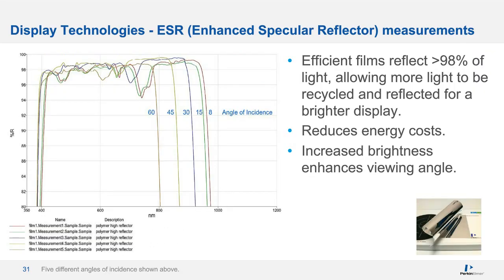Enhanced specular reflectors are mirror-like optical enhancement films that are integrated into the backlight of nearly all LCD displays, TVs, laptops, phones, and more. This reduces the amount of energy needed to power an LCD display and helps broaden the viewing angle by increasing the brightness of light coming through the display. These are shown in the lower right. Not only are ESR films designed to achieve very high reflectance in the visible spectral range, let's say about 98%, but they are required to achieve this high reflectance at any angle of incidence and under any state of light polarization. Therefore, the ESR films need to be measured with an absolute variable angle reflectance accessory, and the URA works very nicely. So we can see the flexible films here. They're very hard to mount in anything other than a horizontal position. And we see the subsequent data at 5 different angles. Once again, we observe a shift to higher energies as we increase the angle of incidence.